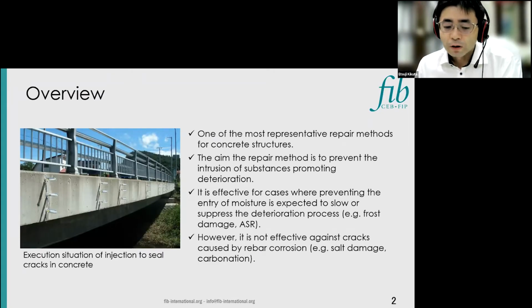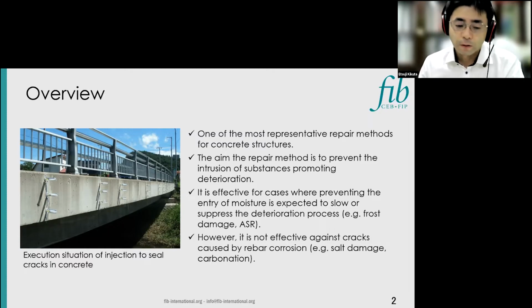Crack injection is one of the most representative repair methods for concrete structures. It is a method that prevents deterioration factors such as water and salt from entering the cracks by filling the cracks with injection materials. It is applicable to both remedial and preventive maintenance. It is effective for cases where preventing moisture intrusion is expected to slow or suppress progress of deterioration, such as frost damage and ASR. However, it is not effective against cracks caused by rebar corrosion, such as salt damage and carbonation.